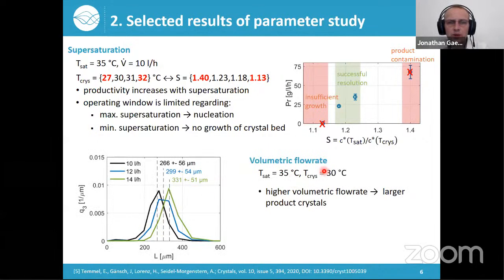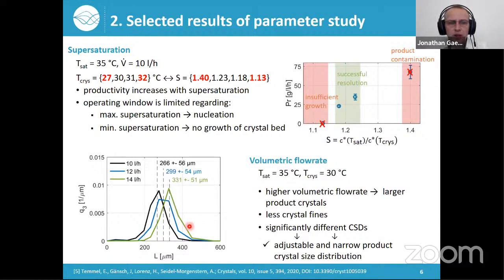Regarding the volumetric flow rate, here you can see 3 product crystal size distributions for 3 different volumetric flow rates, 10, 12, and 14 liters per hour. And we observe that higher volumetric flow rates cause larger product crystals, as expected. But what we could prove with these experiments is first that our product crystal size distributions are quite narrow and we have a very small amount of fines. And also we could see that all these product crystal size distributions differ significantly from each other. So we could prove with these experiments the adjustable and also narrow product crystal size distribution of this continuous process.